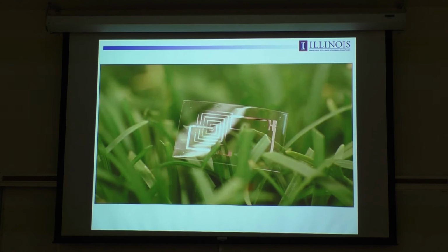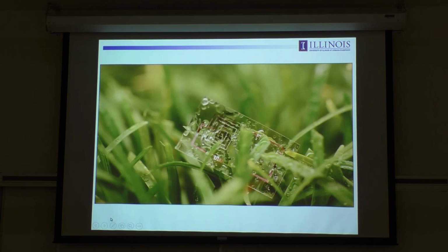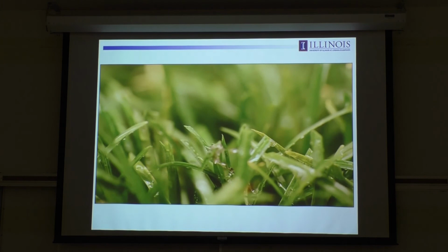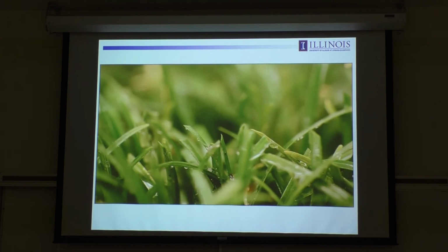and this is what it looks like, you know, under simulated rainfall. This is something we produced in response to a request from a DARPA program manager. But the point is, you can design these things to dissolve at any rate. In this case, it's dissolving almost immediately upon contact with water. It's a silk fibroin substrate, which dissolves very quickly. That's the mechanical support. It takes the magnesium electrode traces with it, which dissolve in a few hours, and then the silicon component's gone in a couple of weeks.